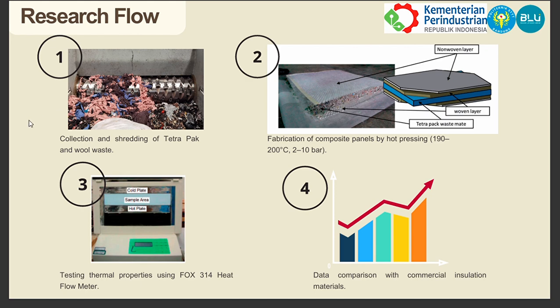And the third, thermal testing. The samples were conditioned at 20 degrees Celsius and 65% relative humidity, then tested using a FOX314 heat flow meter to measure thermal conductivity and resistance. And the last, data comparison. The obtained results were compared with commercial insulation materials to evaluate performance. In short, the process converts packaging and textile waste into eco-friendly insulation composite through a simple and efficient workflow.